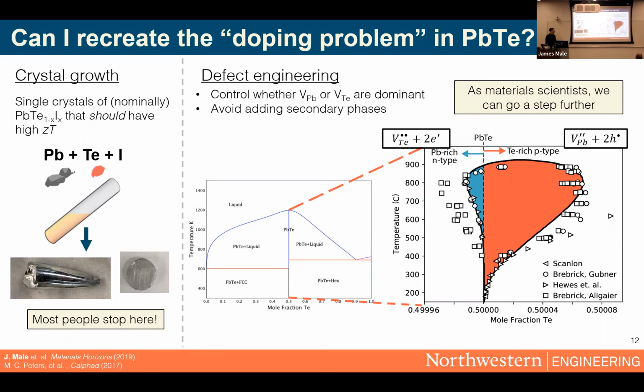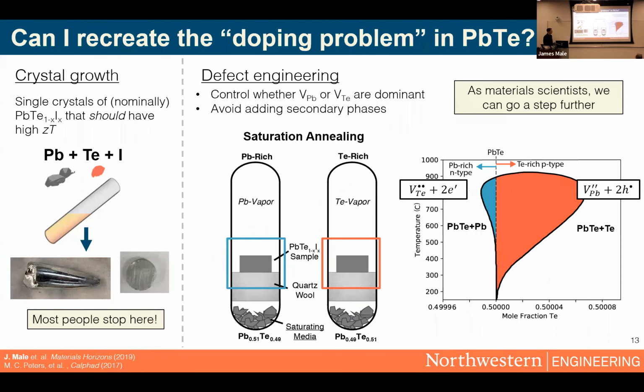So if we zoomed in several times, such that our x-axis is a small fraction of a mole percent, we actually see that there is a phase width that emerges. And the phase width is governed by these different vacancies, which I mentioned earlier, such that something slightly lead rich is going to be N-type, and something that's ever so slightly tellurium rich will be P-type, even without an extrinsic dopant. So I sought to control these defects in the iodine doped samples, and I used a technique